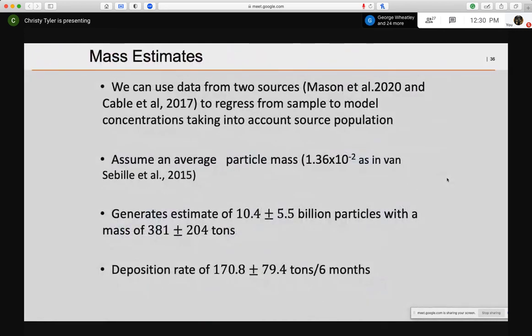So using some mass estimates, looking at 2 different sources that have mass estimates with concentrations in the environment and average particle mass, they are able to get at how many particles may be out in the environment and able to model then the deposition rate. And they estimated that in Lake Erie, the deposition of plastic is about 170 tons of plastic every 6 months that ends up on the bottom of the lake. So that's starting to explain a little bit about where the plastic is going, that a lot of it is probably ending up on the bottom.